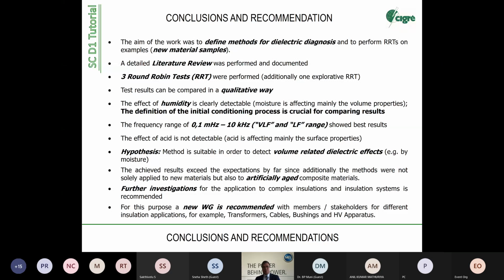The effect of acid is not detectable because acid is affecting mainly the surface properties. And then there's a hypothesis: the method is suitable to detect volume-related dielectric effects, for example, given by moisture or by electrical overstress or by any other chemical-related decomposition of the material that we can detect. But it has to result in a kind of conductive mode, in conductive decomposition products.